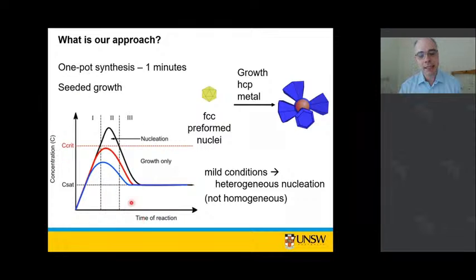So when we're doing this kind of reaction, we really need to control the concentration of the second metal during the reaction. So in this case, if we're growing ruthenium branches, we really need to control the amount of ruthenium monomers or ruthenium zero valent atoms, ruthenium metal atoms in our solution.